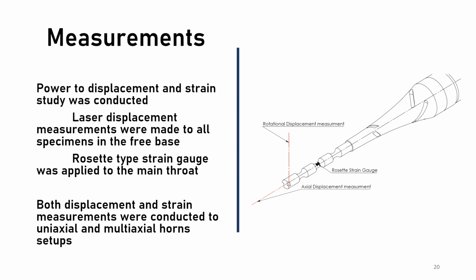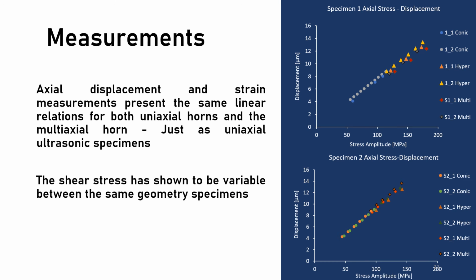So we made displacement and deformation measurements. For the displacement measurements, we applied 2 different vibrometer lasers to the specimen, one associated to the actual displacement, just as tension compression in the actual specimen, and the rotation applied to small machine grooves at the free base of the specimen. To measure the deformation, we applied a rosette strain gauge in the fatigue testing region, the main throat. Displacement and strain measurements were both conducted in axial and multi-axial horns.